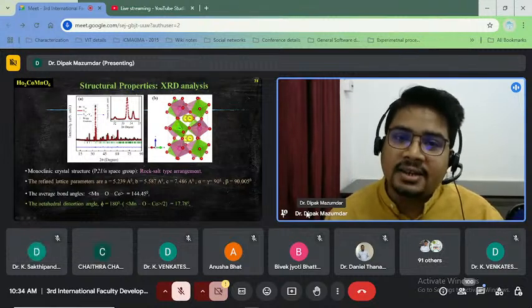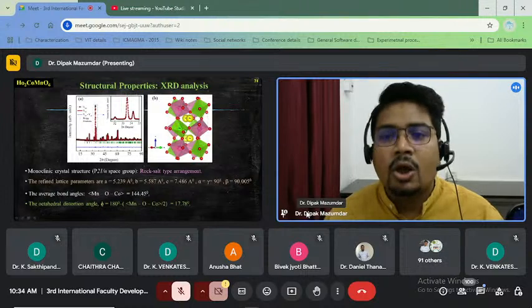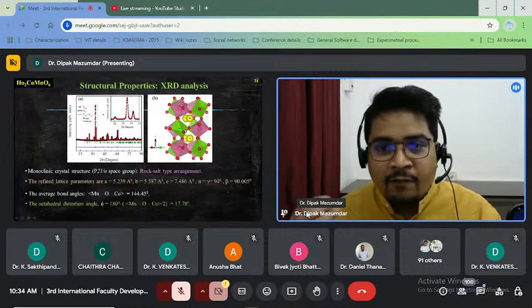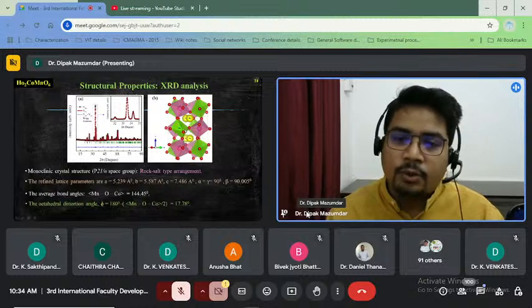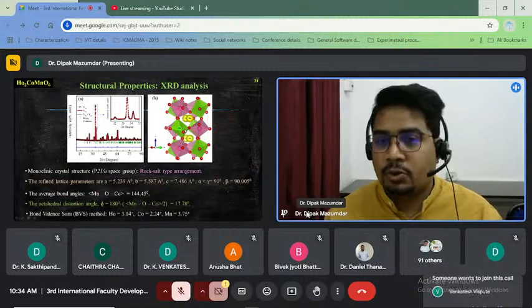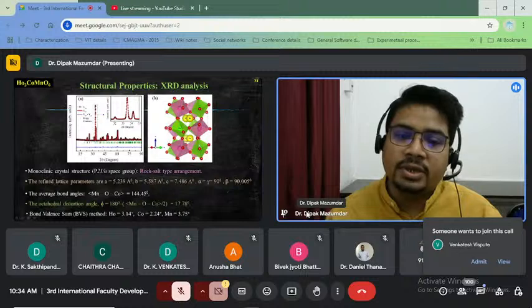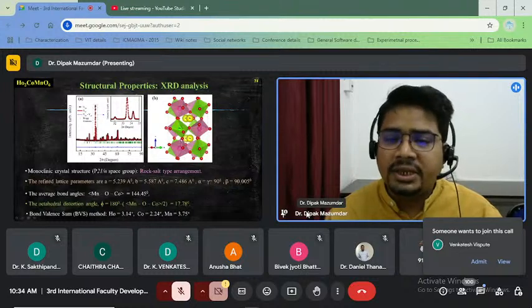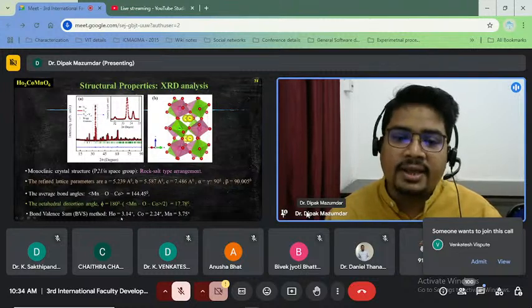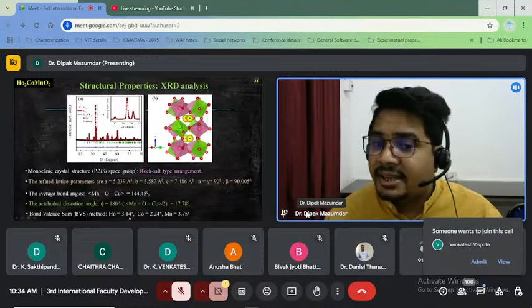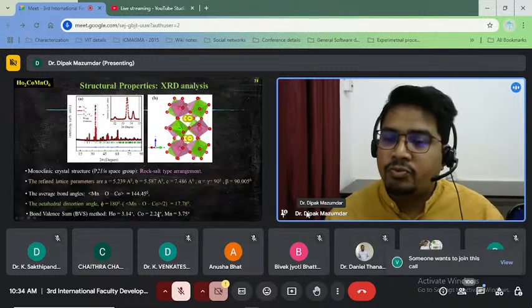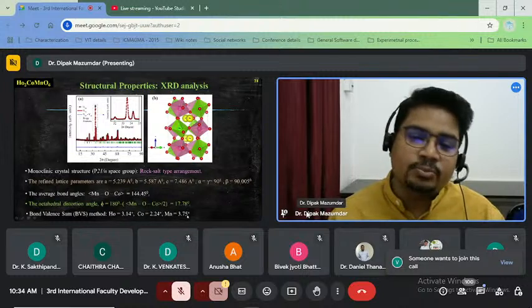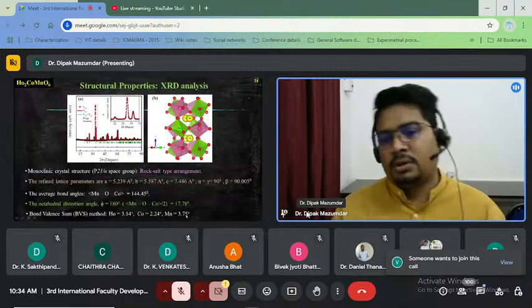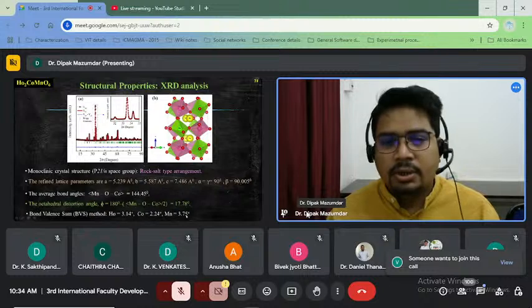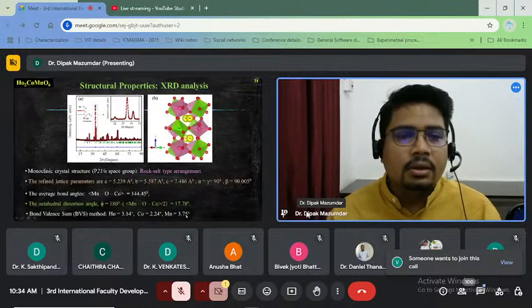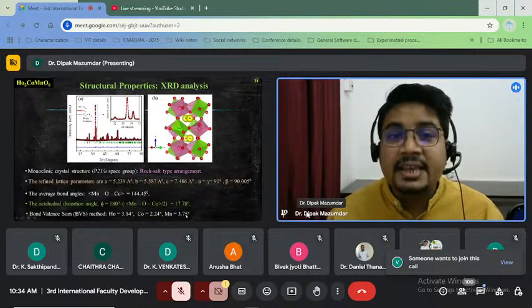And by using this XRD data and this crystallographic structure, we can also determine the valency of these ions, which is known as the bond valence sum method. By the bond valence sum method, we get the valency of holmium as 3.14, which should ideally be 3. Cobalt is 2.24, which should be +2, and manganese is 3.75, which is nearly close to +4. So this is the crystal structure of our compound.